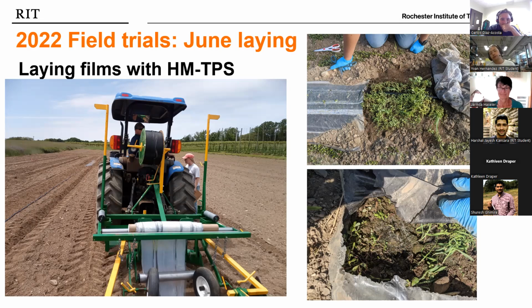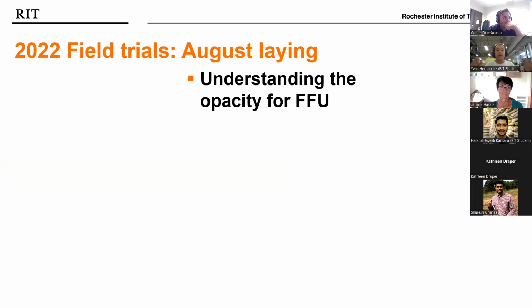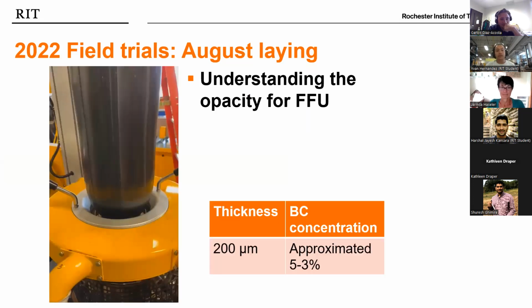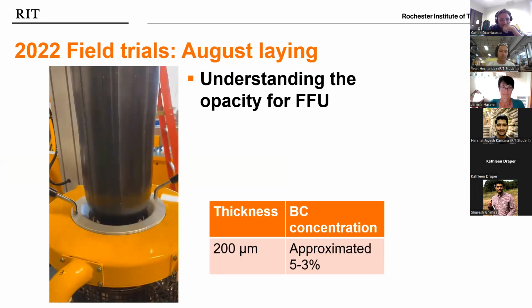So from there, we circled back and tried to, that same year, do another trial to really figure out that fit for use opacity and how much opacifier we needed. So that's where we started to use biochar, which is a sustainable biofiller in plastics that we've worked around. And actually, we published a couple of things about it, and trying to understand what are the things of biochar that are better for plastic filling, and especially plastic films in this case.